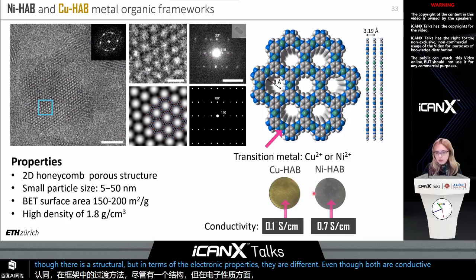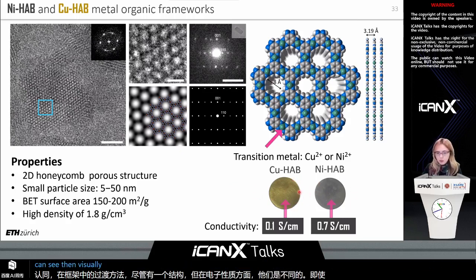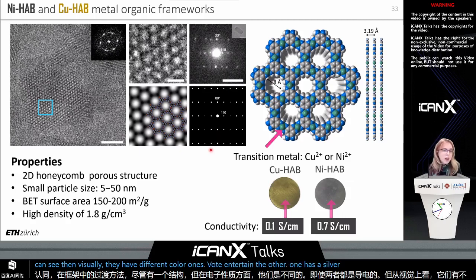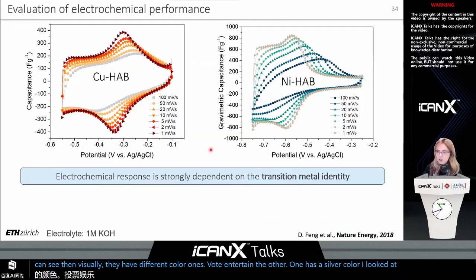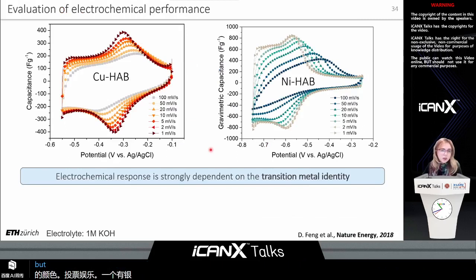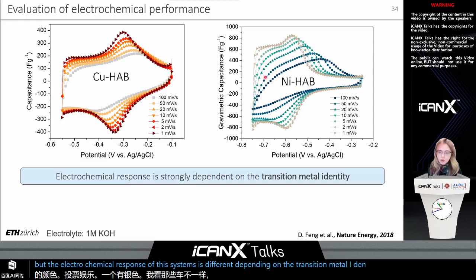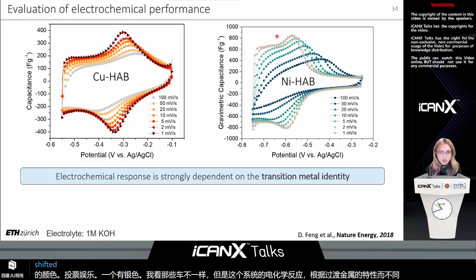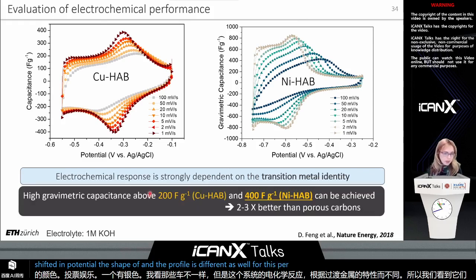But as you can see, even visually, they have different color. One is gold tinted and the other one has a silverish color. Not only the colors are different, but the electrochemical response of these systems is different depending on the transition metal identity. So we see that the peaks are shifted in potentials, but the shape and the profile is different as well for these particular samples.